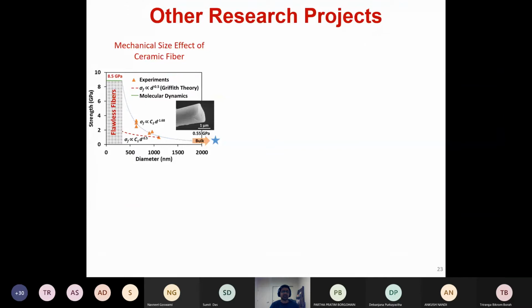So there are some other research projects that I've been working on. I'll just give you a quick 20-second elevator pitch for all of these. One of them is the mechanical size effect of ceramic fibers. If you know Griffith theory, it says that the strength of a material is inversely proportional to the square root of the size of the flaw that the material has. So we started making really small ceramic nanofibers, and we found that they don't follow Griffith theory. Their strength increases really rapidly as you decrease the diameter, and then comes a point where they have no flaw in them, and they become flawless fibers, and they reach the limit strength of the material itself.